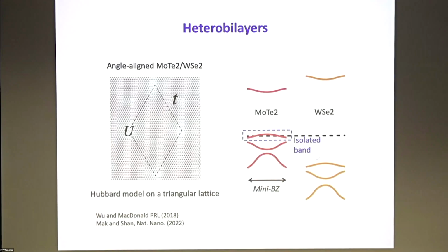So in the heterobilayer, when you have this kind of superlattice structure, you form flat bands in the mini Brillouin zone. So you don't really talk about the big Brillouin zone anymore. You talk about the mini Brillouin zone. For the heterobilayer, you have flat bands in each of the layers, for instance, MoTe2 and tungsten selenide. And to a pretty good approximation, in many cases, you can just isolate one flat band in this kind of heterobilayer structure. And it turns out, in a paper by Fengcheng Wu in 2018, that the low energy physics of this flat band can be mapped to a Hubbard model on a triangular lattice, with the t and the U term. So that's for the heterobilayer.